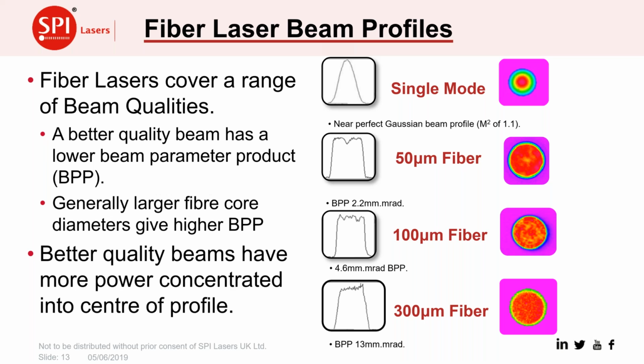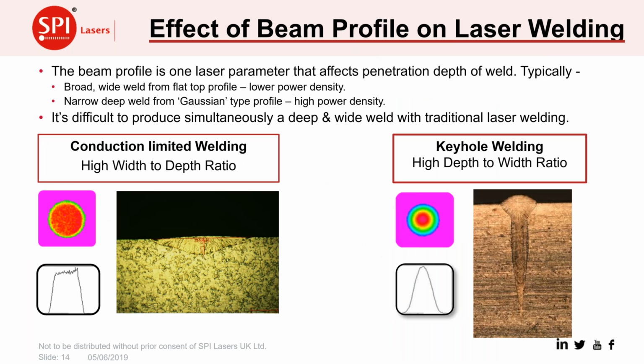So I wanted just to introduce the idea of the laser beam profile, because this is going to be relevant to us later on. From one fiber laser, we might be able to have a range of different beam profiles by fitting different fibers to that laser. Generally, a larger fiber has a larger beam parameter product, a BPP value. And generally, as you go to the higher BPP values, you get a more uniform flat-top profile, whereas the higher quality beams with a lower BPP value tend to have the power more concentrated in the center of the profile. And when we think about that in relation to welding, in standard welding the beam profile is one parameter that affects the type of weld.